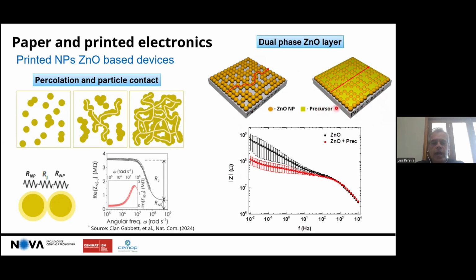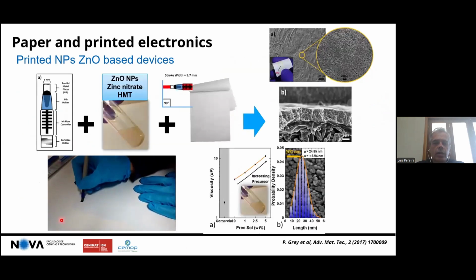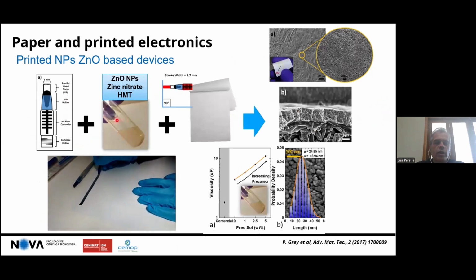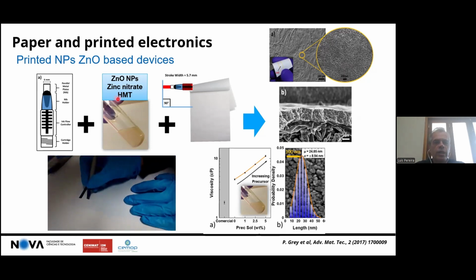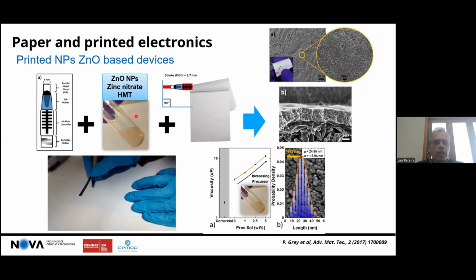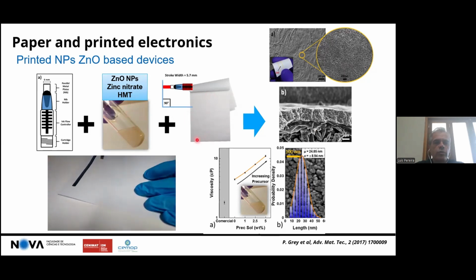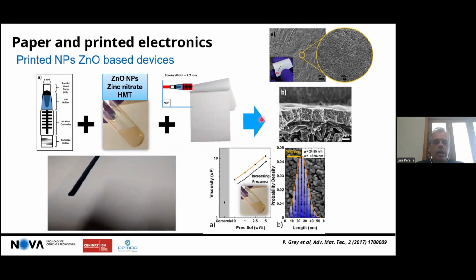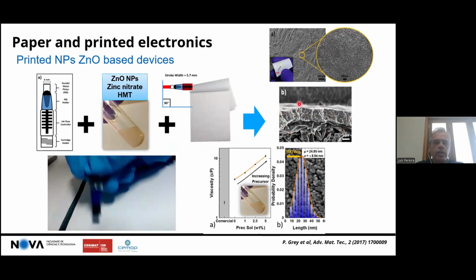This is also another effect that keeps the particles together, which would have some problems staying on the substrate if you just deposit them on top of a paper substrate. So this has a double effect and results very nicely, because you see here that we developed an ink made of zinc oxide nanoparticles with zinc nitrate, and we have HMTA, and we made an ink that could be placed in a pen, and that you can write over a paper substrate. And you see here how the layer results.